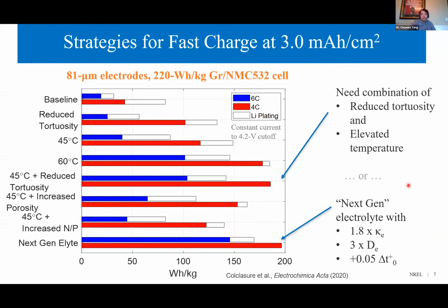Actually, to meet the specific volumetric energy density and cost requirements, that cell loading is not enough. As I mentioned before, it's not enough. An EV cell actually must have a sufficiently high loading of 3 up to 5 milliamp hour per centimeter square.